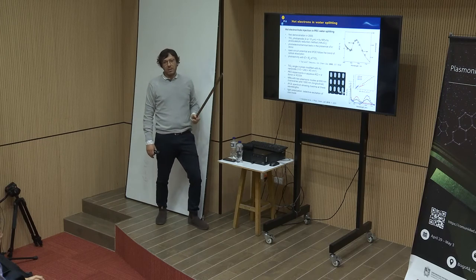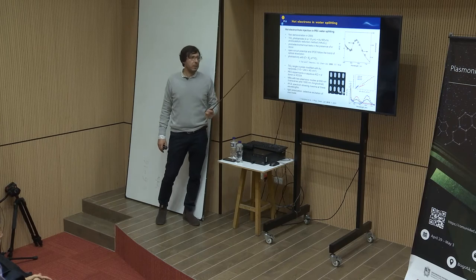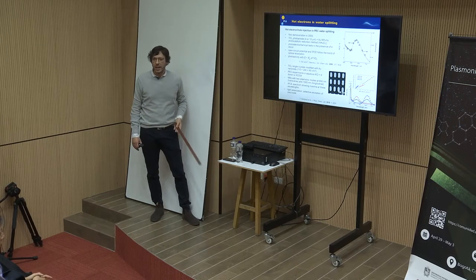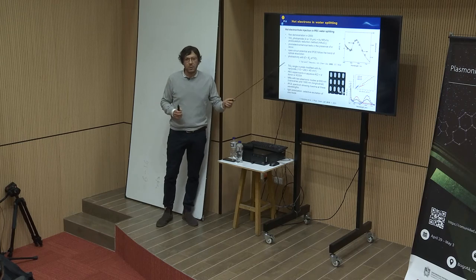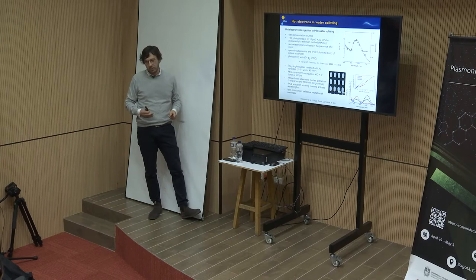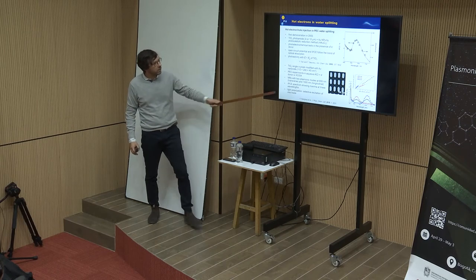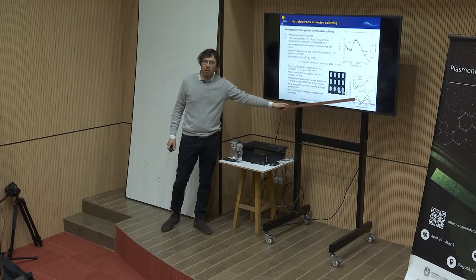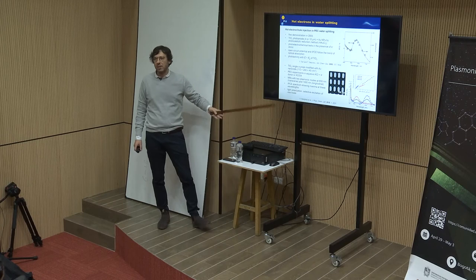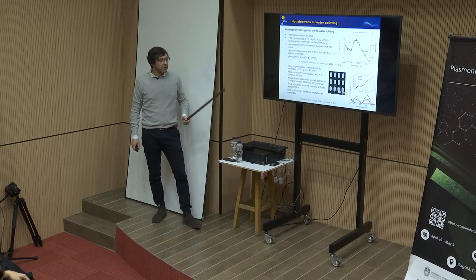And this, of course, is not a really efficient process, again, because we have to excite the surface plasmons. The plasmon should decay into hot electrons, and then these hot electrons should be injected into the semiconductor, and the other charge, the holes, which remain on the metal should react with the molecules, so they should have enough energy to drive a chemical reaction, and this will give you the photocurrent. Otherwise, you will not get the photocurrent. And indeed, okay, this is the IPCE, but I don't trust this very much. But usually, you can get a photocurrent efficiency in the visible or near IR, where the semiconductor does not absorb, in the range of usually 1-2%, or okay, here 6%, 7%, which I never actually saw in my experiments.